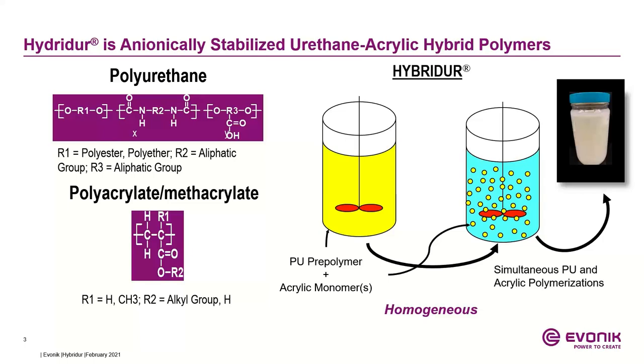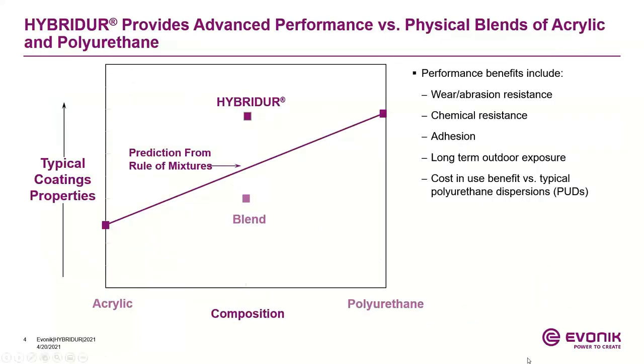The glass transition peak that we get for the Hybridurs is consistent with the interpenetrating network structure these polymers are known for. In the next slide, we demonstrate the coating properties, such as the water, the wear and abrasion resistance, chemical resistance and adhesion, long-term outdoor exposure, and cost in use benefit versus typical polyurethane dispersion. This is using a prediction from the rule of mixtures.